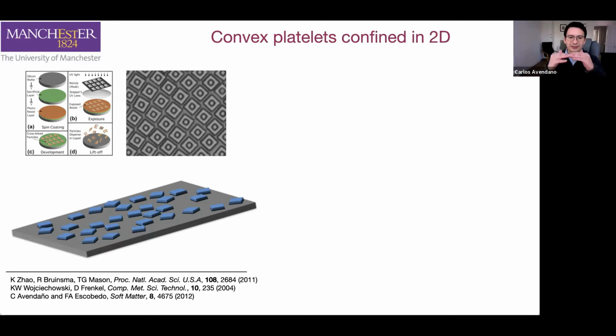And if we tilt this sample to a certain angle, the particles will start sedimenting to the corner of the container. As long as that angle is not very extreme, maybe something like 5 degrees, we will be able to analyze in the same experiment the different phases that are formed as a function of concentration, with the bottom having the most concentrated phases, then in the middle the less concentrated, and at the top the most diluted phases. So again, in one single experiment, it's possible to obtain all the phase behavior for these systems.